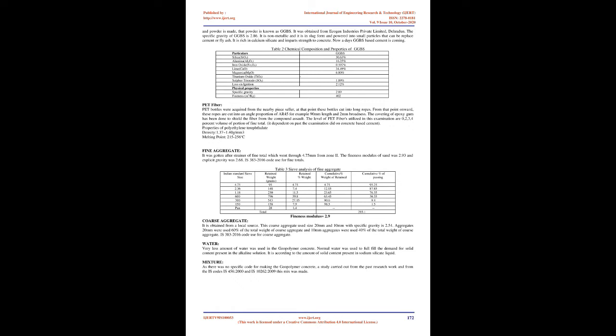Rovnanik, 2010, investigated that curing temperature has a significant impact on hardening and geopolymerization of mineral-based geopolymer. At ambient and higher temperature, the sample practically set in the initial 4 hours. Conversely, the setting was delayed for a period of 4 days when the mix was kept at a temperature of at most 10 degrees Celsius, yet this doesn't influence the grade and properties of the cemented geopolymer product at the age of 28 days. Accelerated strength formation was seen on rock-based geopolymer cured at 40 to 80 degrees Celsius. It is worth mentioning that the impact of temperature depends on the duration of curing.